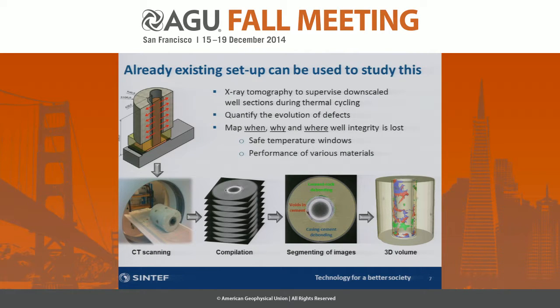So we wanted to get some experimental-based information on this case. And we decided to do that by using an existing setup that we have at SINTEF to study how temperature variations actually affect the well. And we have a setup where samples, as you see here, with rock, cement, and casing, can be exposed to radial temperature variations. So this green slab that you see here is just isolation, and the temperature variations in this case are purely radial. So this copper rod is both heated and cooled at a very controlled rate, so you can put temperature cycles at will between -50 and 200 degrees on this temperature platform.